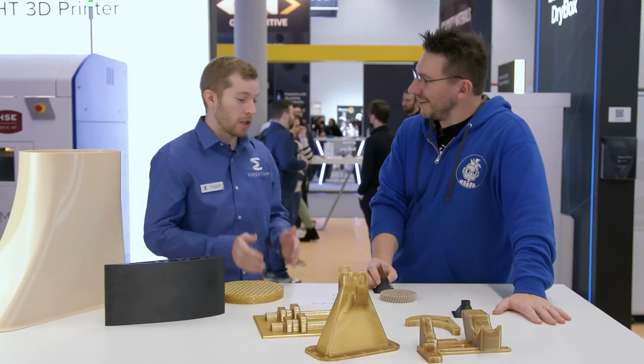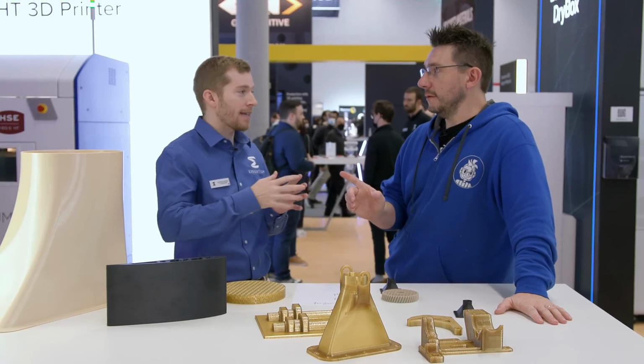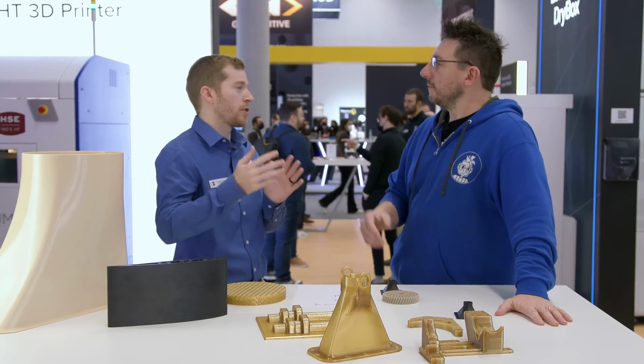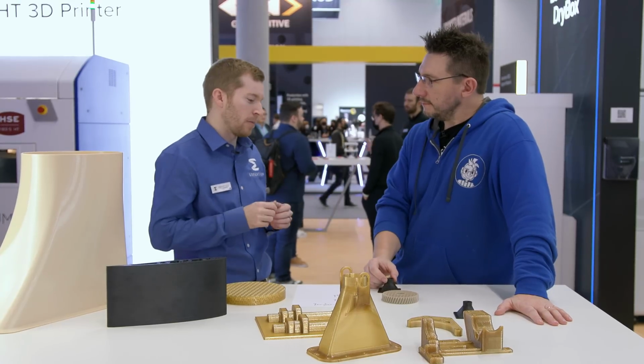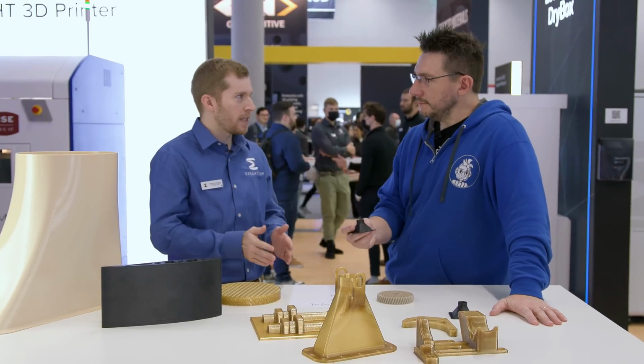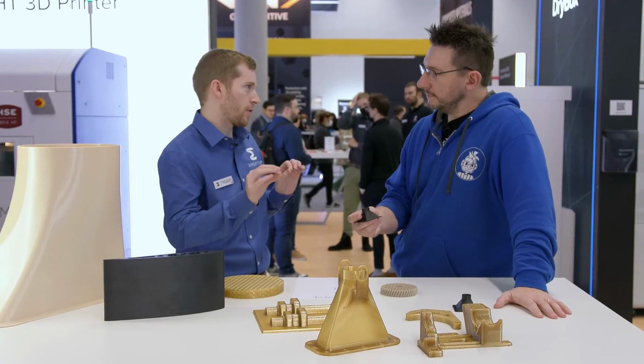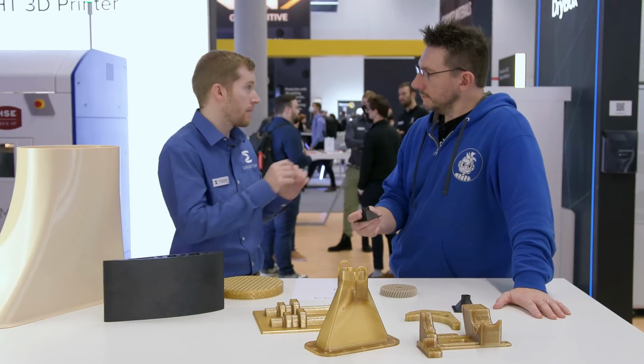Some materials are low crystallinity and some are high. Meaning the size and the number of meatballs, the proportion, the fraction of how much of that polymer structure is actually crystallized. So PLA, when you print it and it cools, is almost amorphous. There's very, very little crystallinity in that PLA polymer, but it is semi-crystalline.